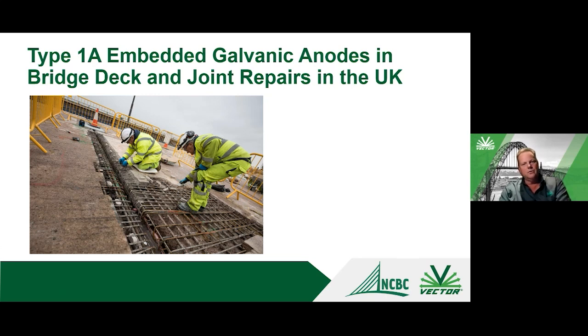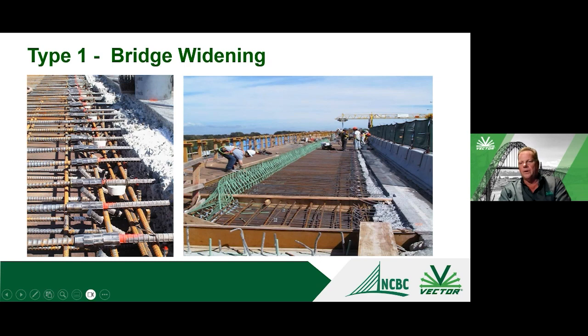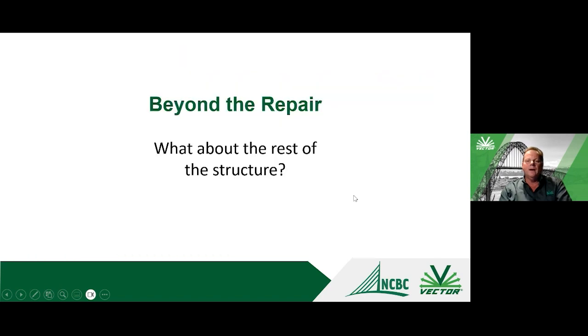There's a large project in the UK, as an example, where you had a combination of anodes used at these interfaces around joint repairs and throughout some larger concrete repairs on the deck. You have other places where you might see this interface between new and old concrete, where you have a corrosion risk. And one area is bridge widening, and you see the anodes placed along this interface. And any type of structural modification could be an area where you have a new and old concrete interface. So that's really just another method to help the investment in the repair last longer.